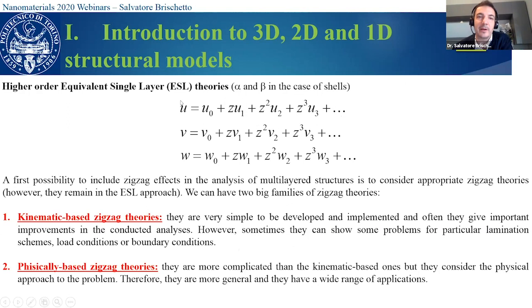So for example, in the equivalent single layer approach, which means that we consider all the multilayered structure as one equivalent structure, the expansion for all the displacement components is written for the whole multilayered structure. In this notation, you cannot see the dependence on the K layer, which means that we do not write the expansion for each separate layer. So in this case, we improve the results, for example, for very thick structures, because we introduce the thickness stretching effect. But we can have some problems, for example, for structures which have a high transverse anisotropy, because in this way we cannot obtain the typical zigzag effect. Okay, the zigzag effect can be introduced in an artificial way.